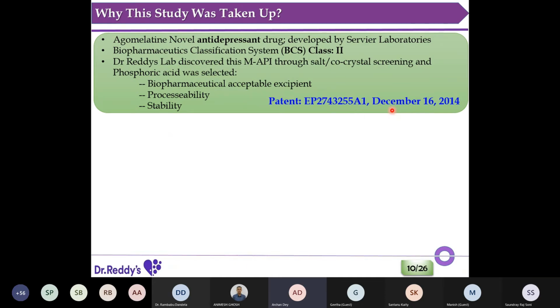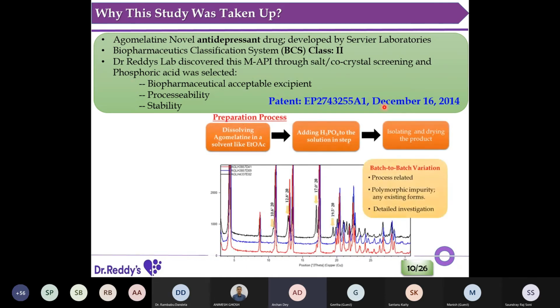Okay, and this is the process as per the patent. It's a very simple process: dissolving the agomelatine in a solvent like ethyl acetate, and then adding the phosphoric acid to the solution in a step. Of course, you get some precipitation upon addition of phosphoric acid, then isolating and drying the product. So it looks like a very simple thing and very easy to do.